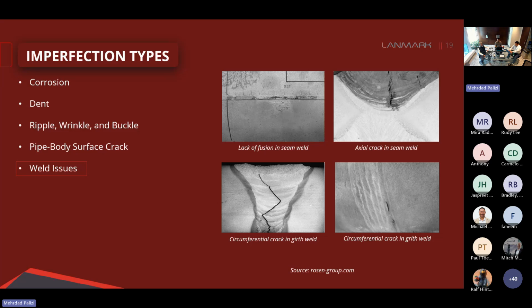This is because the weld and heat affected zone around it, they might have different metallurgy. There might also be residual stresses at these locations if post-weld heat treatment is not performed. The main integrity concern about weld issues is that they might behave like cracks, and under operating conditions, they might grow over time.